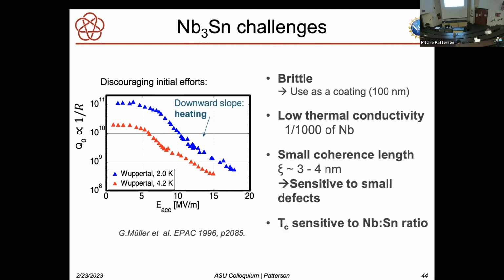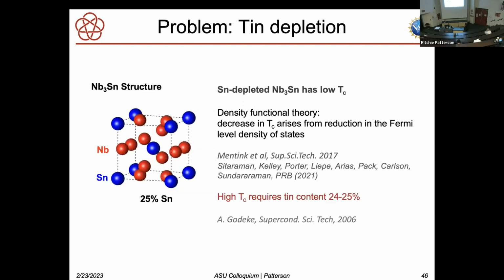And finally, the critical temperature turns out to be very sensitive to the concentration of tin, whether it's really niobium-3 tin or something a little off from that. And so let's look at that. So here's one problem: having too little tin. So here's the niobium-3 tin structure. And this is what you want.